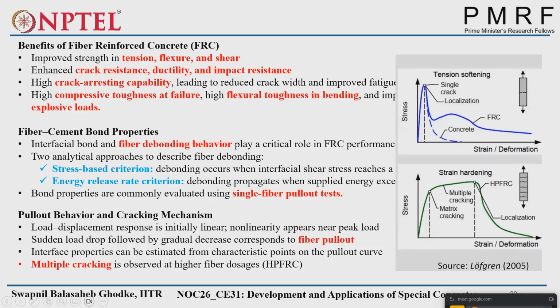So how the post-peak behavior changes, you will see. This is the normal concrete. This is a stress versus strain graph. Once it is loaded and the first single crack appears, the graph will go down like this for normal concrete. But in the case of fiber reinforced concrete, the crack will happen, then fiber pull-out will start from here, and the post-peak behavior will show. It will not suddenly fail, but normal concrete will fail like this only. So that's why the fiber pull-out test is very important, and here this shows the fiber pull-out.